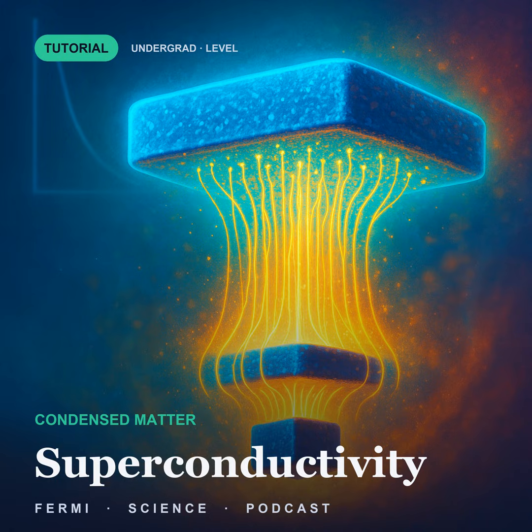Bascom Deaver and William Fairbank at Stanford, a tin film electroplated onto a copper wire 13 microns across. Robert Doll and Martin Näbauer in Munich, a lead film on a quartz cylinder read from the torque on a suspended fiber. And the quantum is about 2 times 10 to the minus 15 webers, the Earth's field through a square roughly 6 microns on a side.